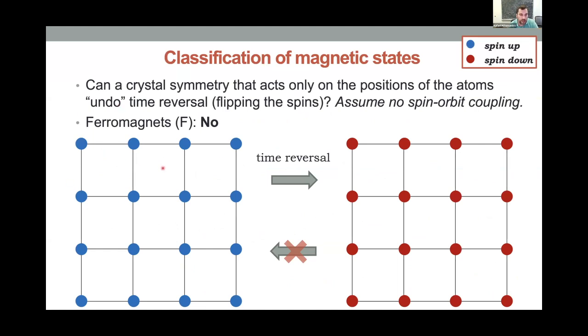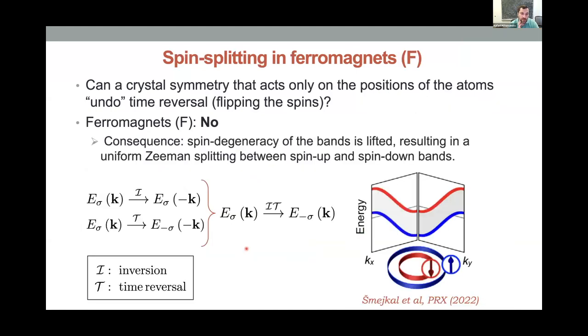Okay, so again, I will start with a very brief overview, just so we're all on the same page. The question that we want to ask is what kind of symmetry I have that when I combine with time reversal leaves a magnetic system invariant, and assume that we have no spin orbit coupling. So I'm really talking about combining crystalline symmetries with spin symmetries. And if I have a ferromagnet, there's no such symmetry, right? If I apply time reversal, I flip the spins, there's nothing I can do that brings me back to where I started. And as a consequence, as we know, the symmetries that make the spin bands degenerate are no longer satisfying, and you get a spin splitting of the bands, okay?